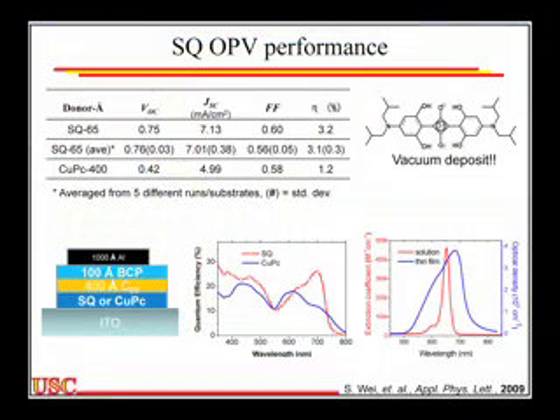So the next challenge was, how do we get high extinction and broad lines? The next high extinction molecule is one that's well known to a lot of people in this department. I know Seth's group has done a lot of work with squaraines looking at the NLO properties of them, really tied to the same things we're looking at here: very high extinction, very high polarizability, and so on. These are stolen out of this paper, but you can see these all have extinctions between 10 to the 5th and 10 to the 6th, which is really good. These are small molecules with very, very high extinction coefficients.